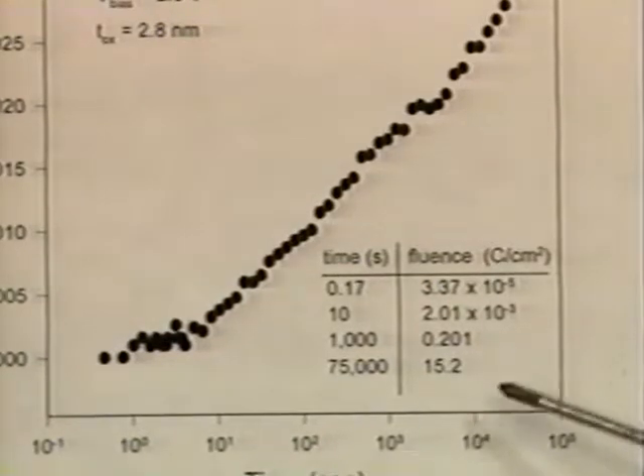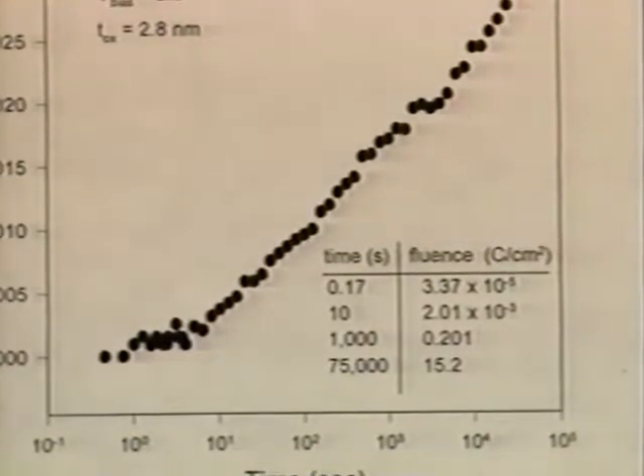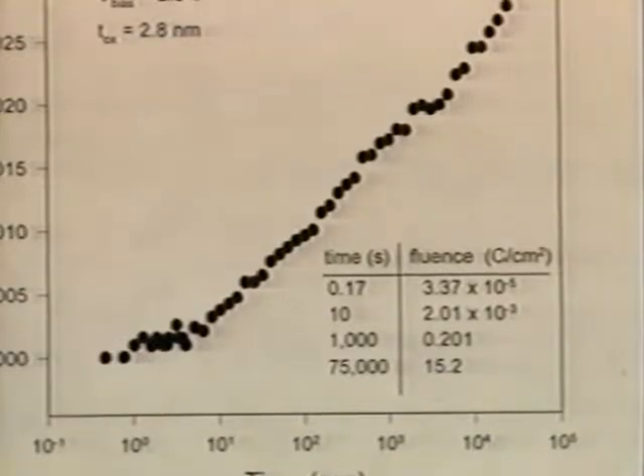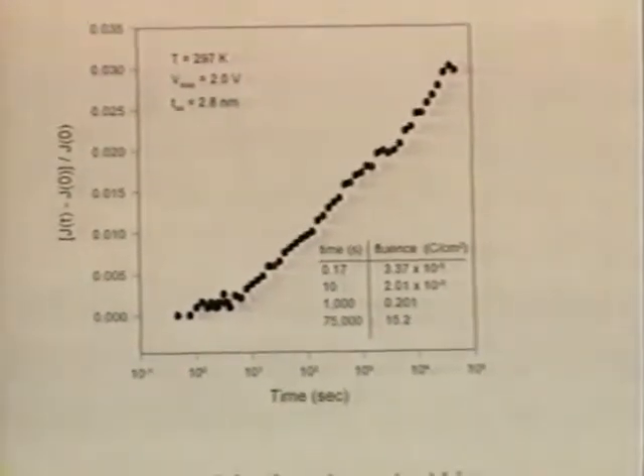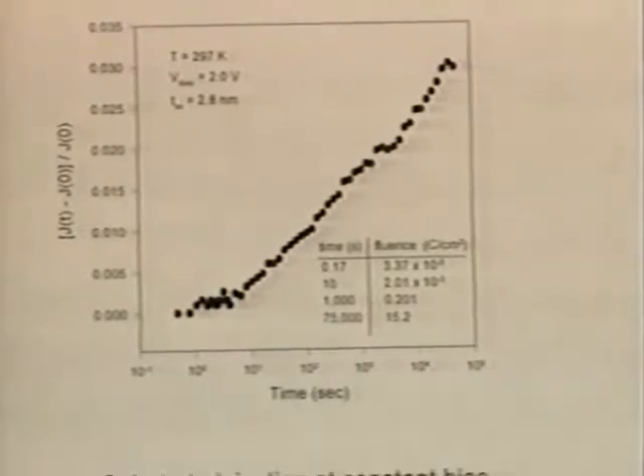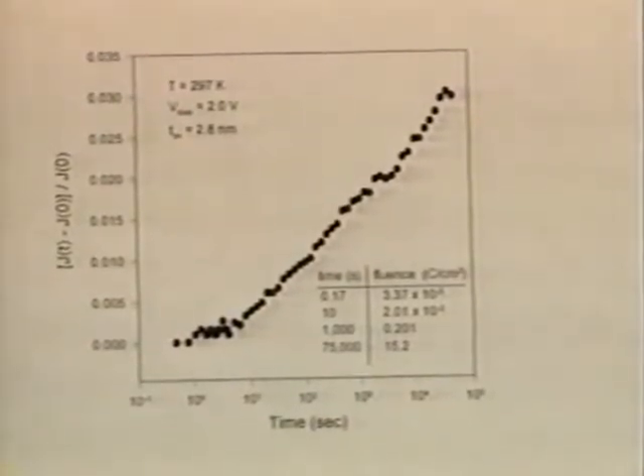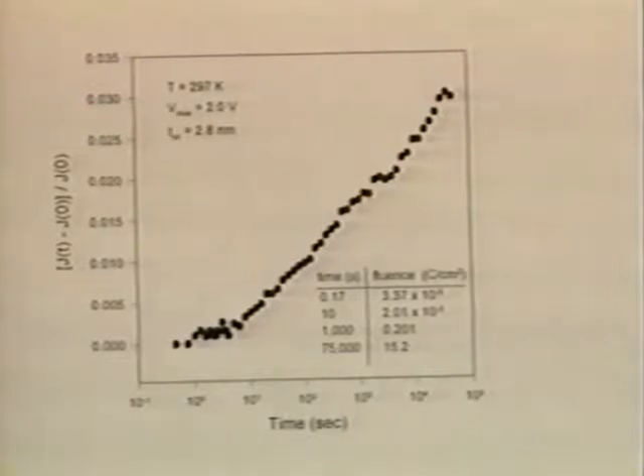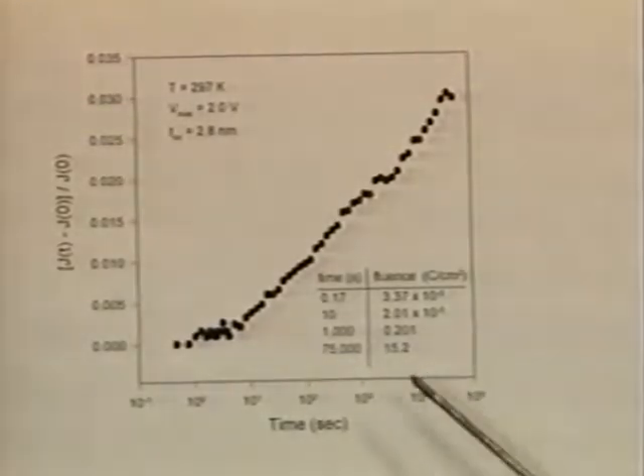And you know that charge to breakdown numbers typically in oxides are 1 to 10 coulombs per square centimeter, but you've also heard rumors about how as you decrease the oxide thickness, the charge to breakdown increases exponentially. Have you heard about that? That there's a really strong increase, and I'll be addressing that later on, but clearly you can put a huge amount of electrons through these devices.